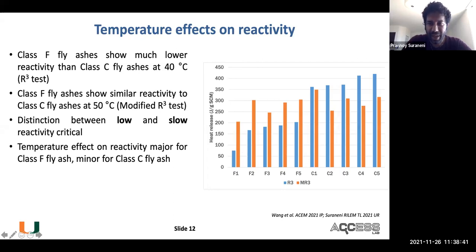On the other hand, if you look at the modified R3 test, there is very little difference between class C and class F fly ashes. You can see that all of these have very similar reactivity as opposed to these, which have significant differences. So what this means is that the modified R3 test is getting out quite a bit of the reactivity of the class F fly ashes. On the other hand, the R3 test, which is run at 40 degrees, is not.